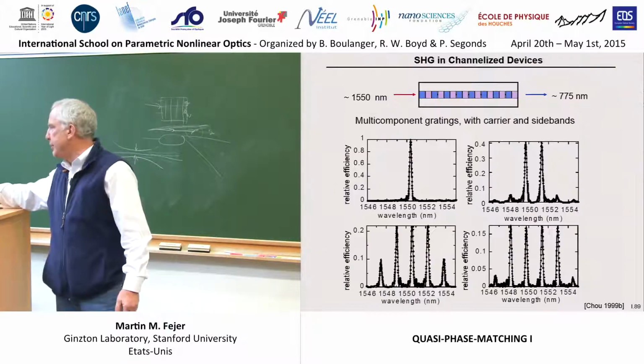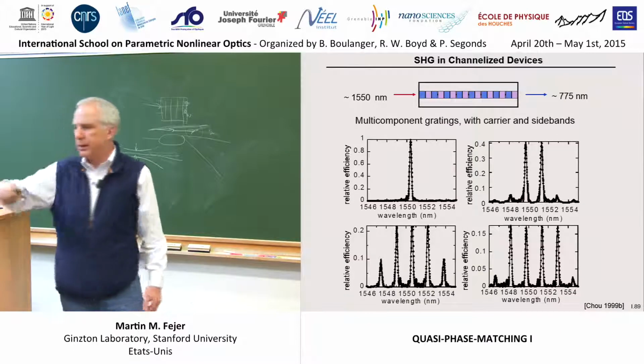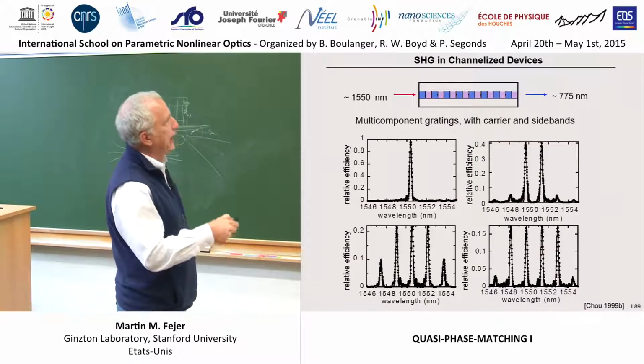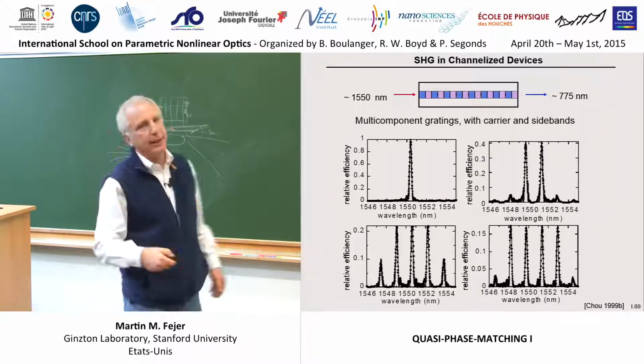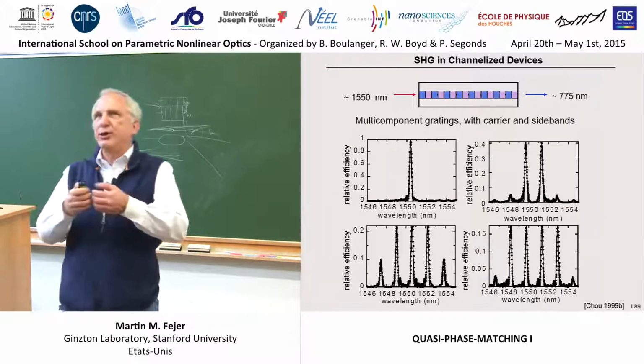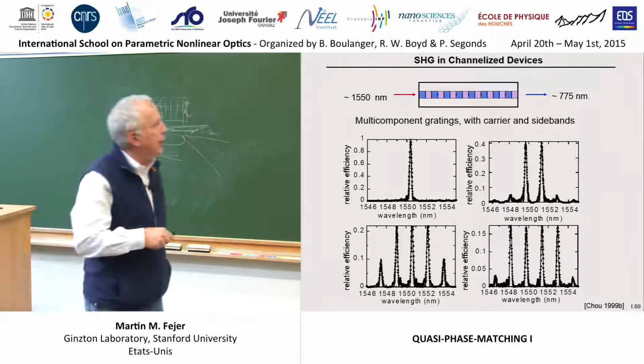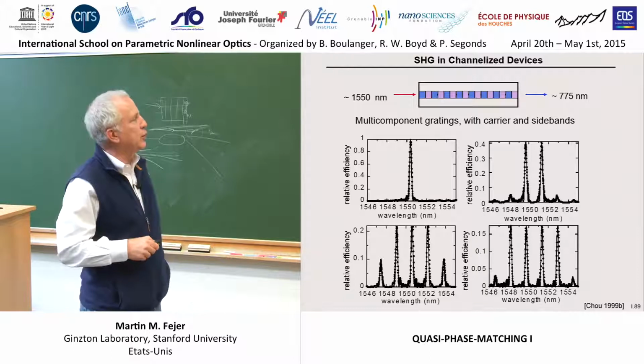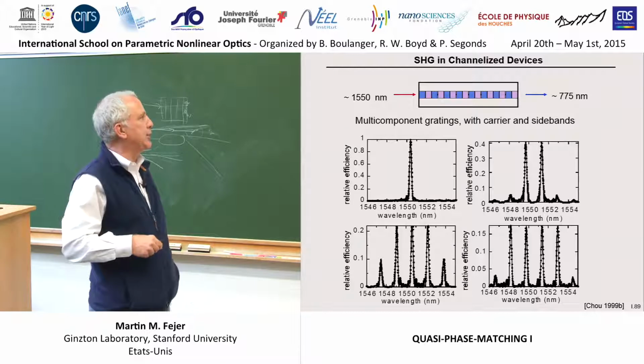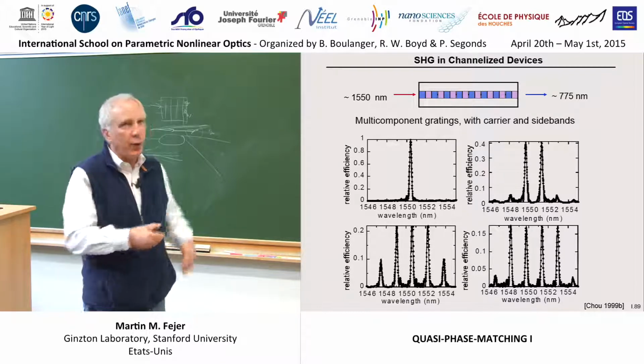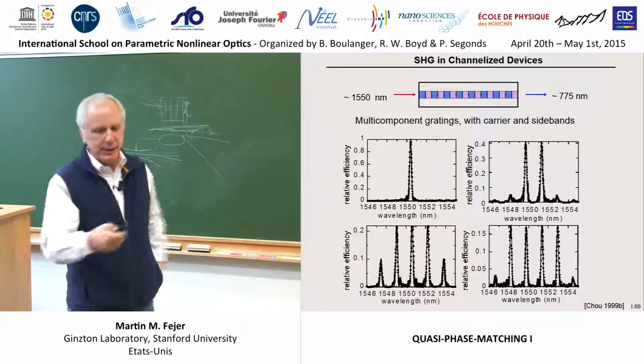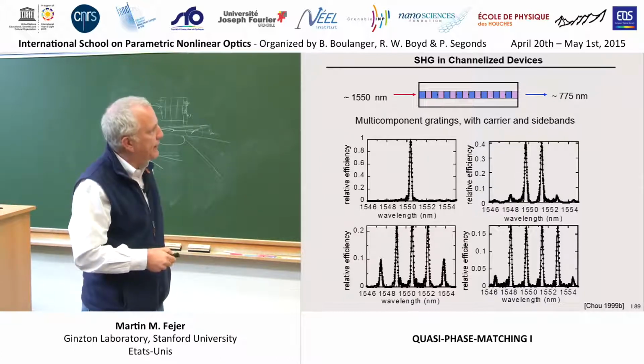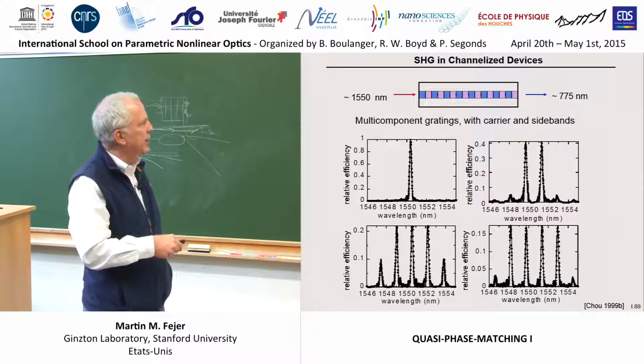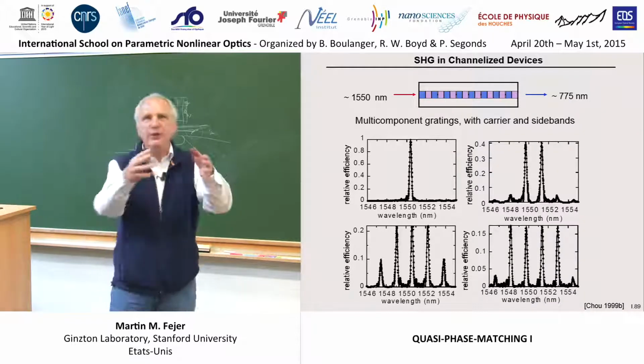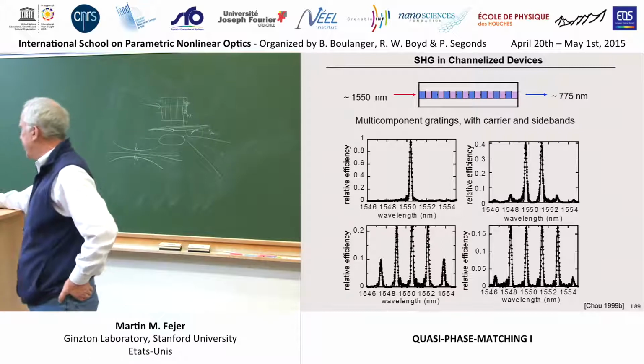And that was what was done to make this thing, was just add more and more sinusoidal components to the grating. Since this is sort of a phase-only filter, it says that the area under this curve should stay conserved. So if you split it into 2, they should be half as high. If you split it into 3, it should be 1/3 as high. If you split it into 4, it should be 1/4 as high to keep the area constant. And that's roughly obeyed here, but we have these side lobes that take some of the energy, so it's a little bit more reduced than that. But roughly speaking, you would expect to conserve the area under those curves.